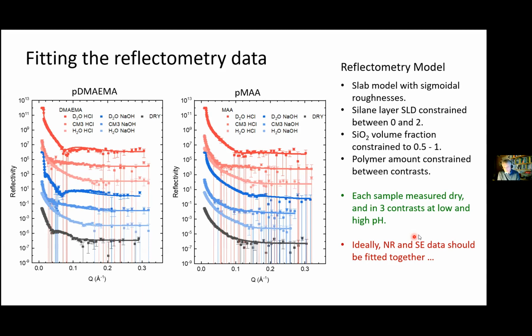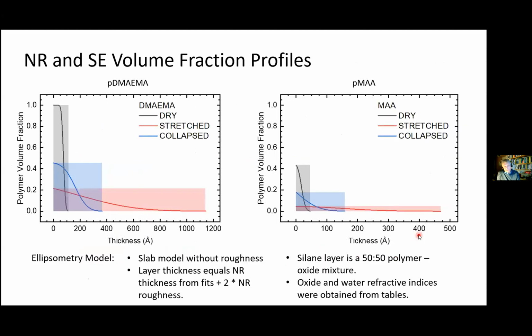I'll show an example of what you can get from the fitting. So from the reflectometry data, we obtain volume fraction profiles under dry, stretched, and collapsed conditions. Here we use the thicknesses obtained from this fitting as input to the ellipsometry model, and then calculate the optical properties from the ellipsometry model with this data.